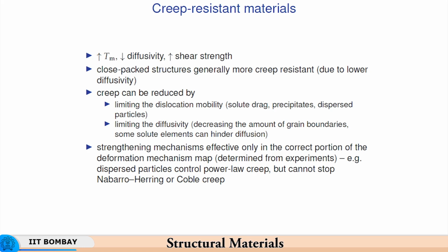This would prevent any kind of grain boundary movement, because they just do not get dissolved in the parent matrix even at high temperatures. Similarly, limiting the diffusivity, you decrease the grain boundaries, that is the whole idea of grain coarsening, because we have seen that all diffusion based processes of creep are sensitive to grain boundary area. So, grain boundary area is an extremely important parameter to permit creep by grain boundary sliding in particular. Both Nabarro Herring and Coble creep are non-linearly proportional to the grain size, and therefore the lower the grain size, the higher the creep rate for both these processes.